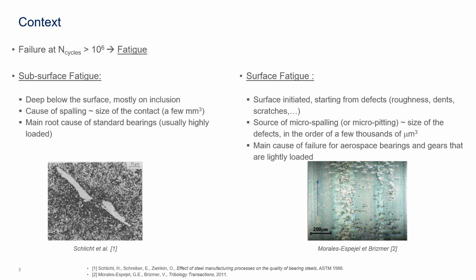Okay, then what about classical failures? On the left, you can see some butterfly. As I said before, you have the inclusion in the middle, and you can see the two wings of the butterfly. And so you can see some cracks here. Typically, the cracks occur at the boundary between the wing and the steel. Yes, this is what we call a typical subsurface rolling contact fatigue.